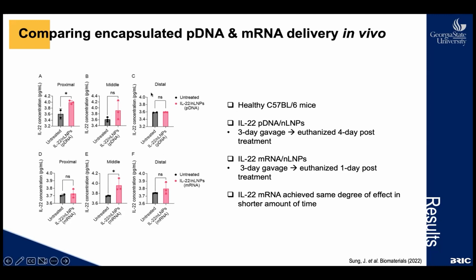For the DNA, IL-22 was increased in the proximal colon after 4 days, but the IL-22 level was increased in the middle colon in the mRNA group. This shows that a shorter time was given to the mRNA group, but it traveled further and showed an increased IL-22 expression level. This tells us that mRNA would be a better therapeutic agent to test in the ulcerative colitis model.